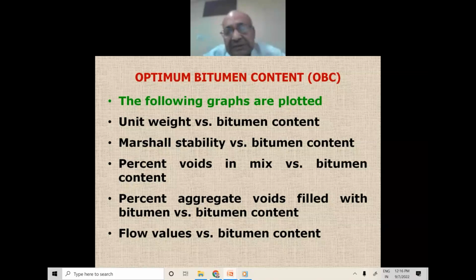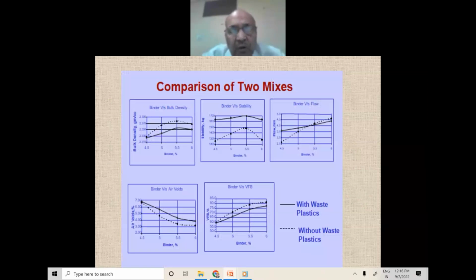After that, all the specimens are to be tested in water controlled at 60 degrees plus minus 1 degree for 30 to 40 minutes. Take out the specimen from the water bath and place it in a breaking head. Place the breaking head in the Marshall testing machine and the load is applied on the breaking head by the loading machine at the rate of 5 centimeter per minute.